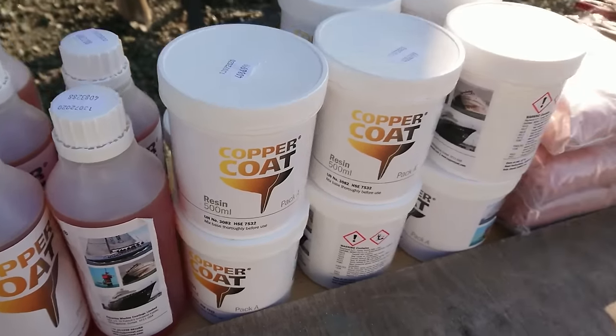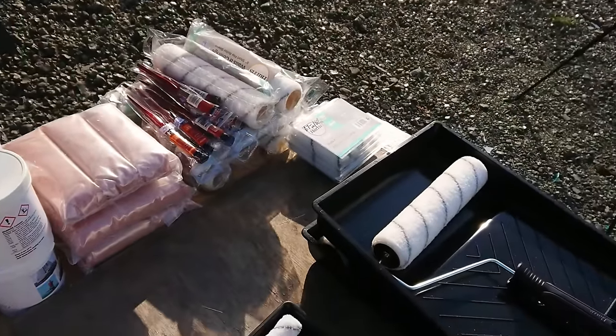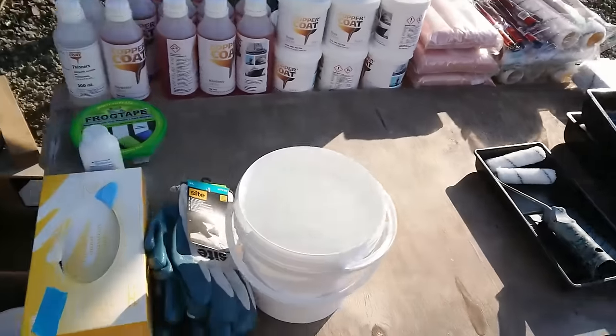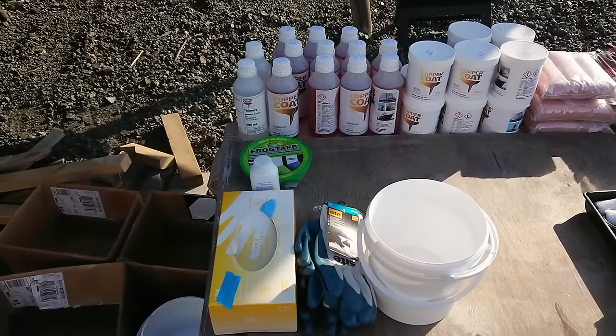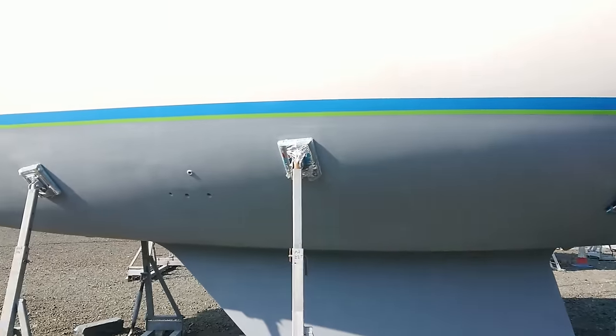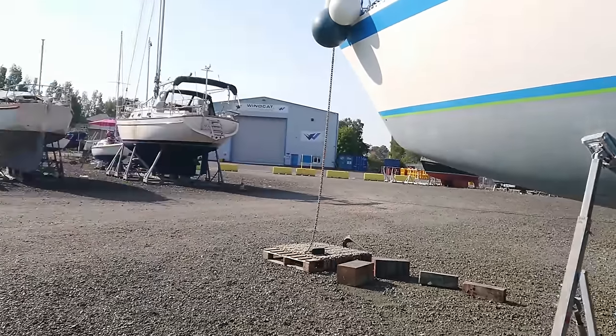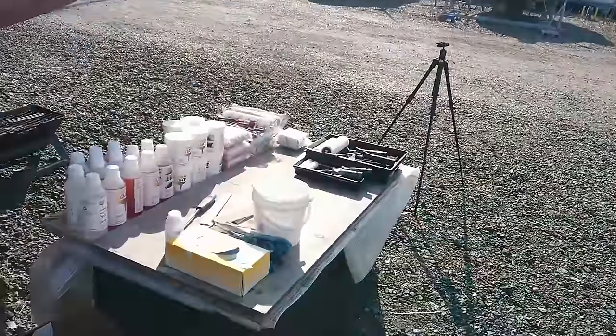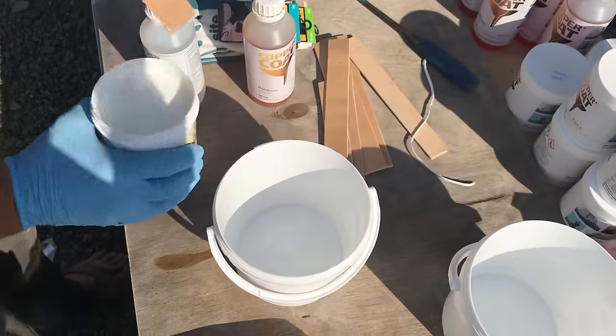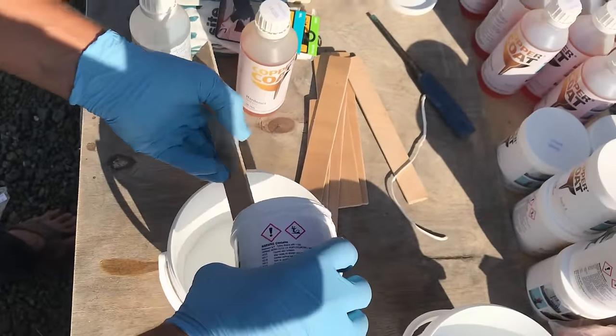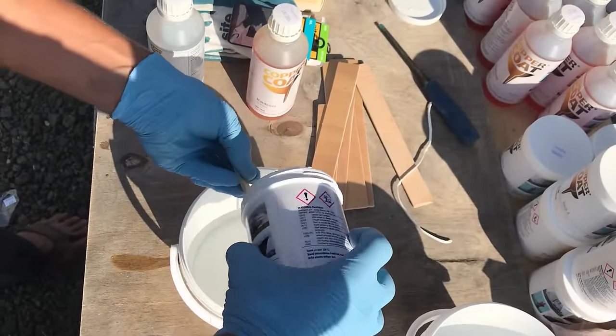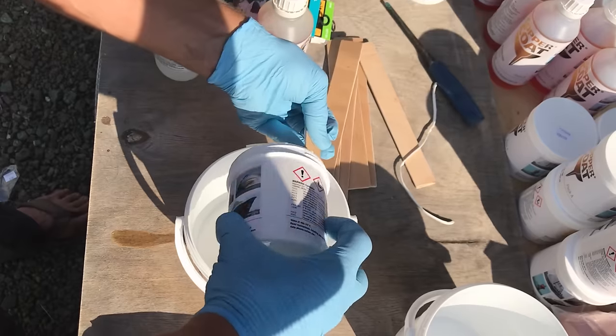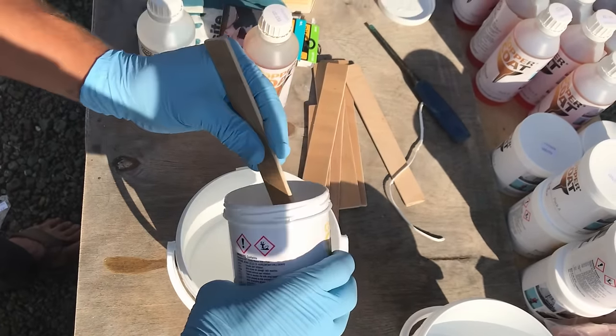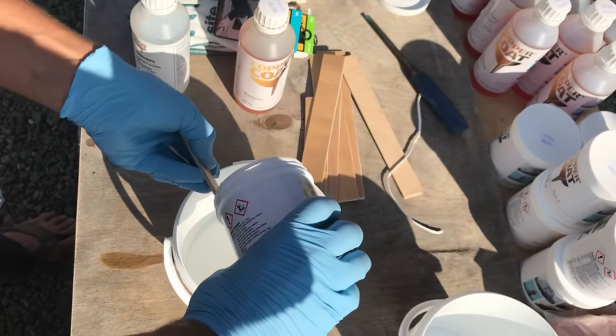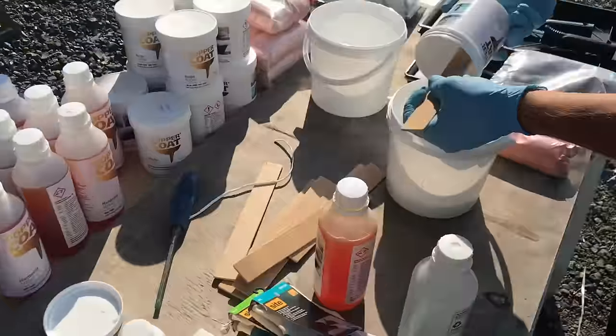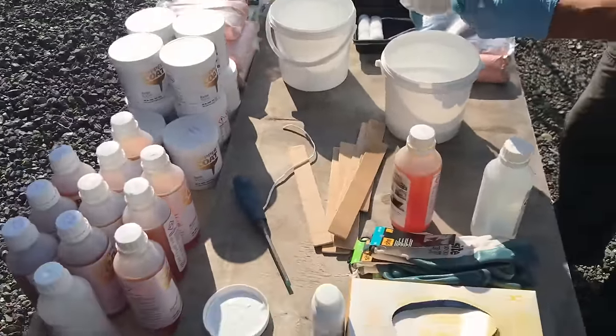Like with all epoxy resins, you need to apply each coat over the top of the next while it's still tacky. Though with this, if it's applied while the previous coat's still too wet, you'll just lift that previous layer right off with the roller. Apply it when it's too late and it's dried too far and it won't bond properly and it'll lightly blister. And we need to make sure we get all five coats done in one day. There was only going to be two of us doing the painting, so by the time we finish one coat, it should be tacky enough for us to start the next.